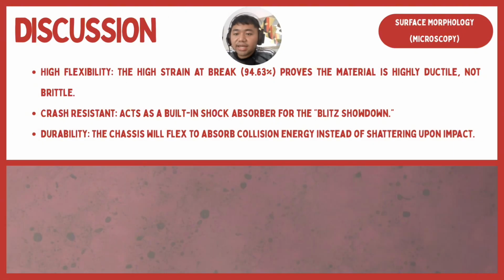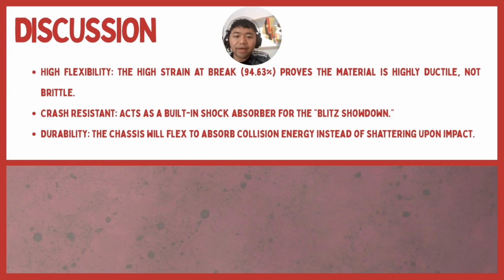Now let's connect this physical property to our microscopic findings. Our earlier results show some minor microscopic pores and trapped air bubbles at 20 times magnification. These micro bubbles are just a normal consequence of manual hand mixing and room temperature curing. The key takeaway here is that despite the tiny air pockets, the material still achieves great tensile strength and incredible ductility. This proves that the minor mixing inconsistency did not compromise the structural performance of our ram and bumper during the match.